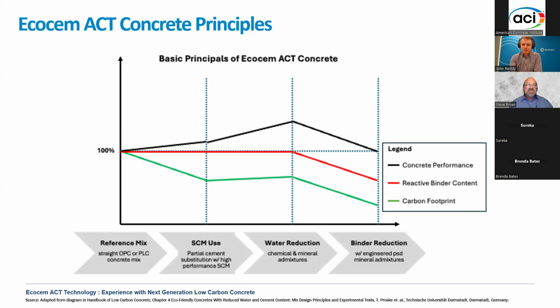You didn't raise the cementitious content, and perhaps you raised the embodied carbon slightly due to the embodied carbon brought in by the superplasticizer. But then the magic is when you reduce the cementitious content to bring the concrete performance back to the original 100%, you're able to significantly reduce the reactive binder and the carbon footprint. The trick is to do all that and maintain workability and be cost effective.